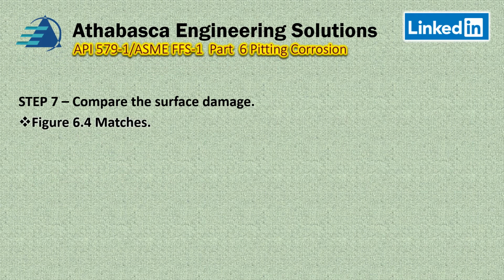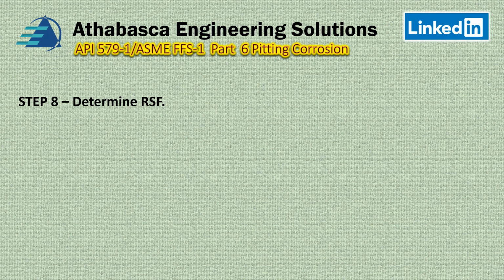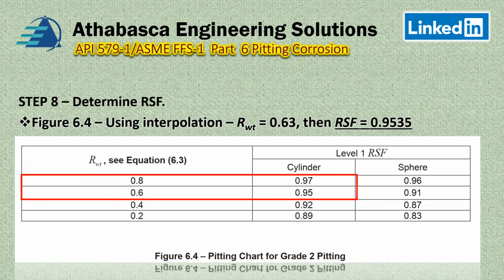We get our figure matched up, then part of that figure is a chart shown below here. So we know RWT from equation 6.3, we calculated that earlier, and we know we're a cylinder. So let's go and determine our RSF factor. As we continue here, we're going to continue with step eight, which is determination of the RSF. Now we go back to this figure again, and basically our value is 0.63, so we're in this range. Basically all we're using is interpolation between 0.6 and 0.8, and then going across for the cylinder. And basically when we do that, we get an RSF of, the exact answer by formula is